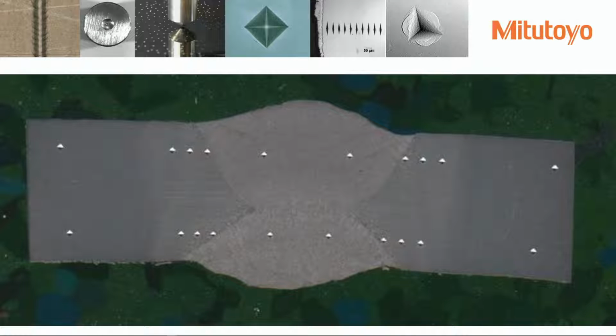So this is one of my favorite pictures because it's really a good demonstration of what's happening on this weld nugget. Okay, you have the 2 pieces that you welded together on the outside. Those are tested in the non-heat treated zone. You have the heat affected zone tested, and then you have tests in the weld nugget. Generally you don't etch samples, but in this particular application they did acid etch it to better show us what's happening here.